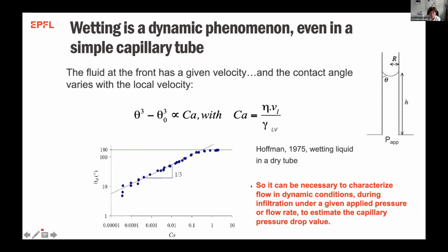When you do liquid composite molding, most of the time you have a pressure. So it's not just a capillary rise that you measure, but a capillary rise with a given pressure below forcing the fluid. And what we know from a long time ago with the experiments in tubes is that the contact angle is a function of the velocity. In fact, what was found is that this contact angle varies with the capillary number to the power one third.